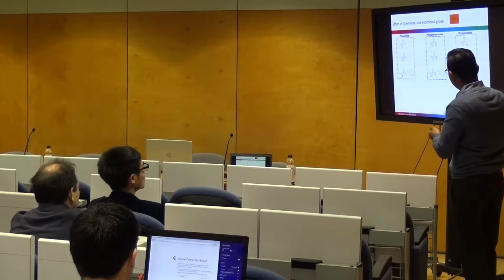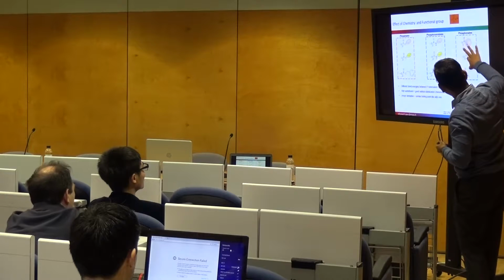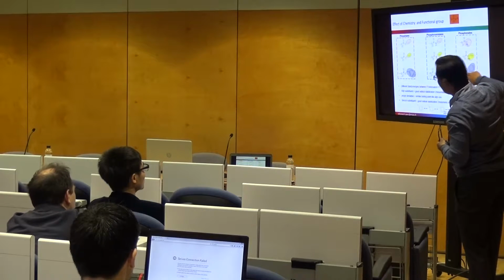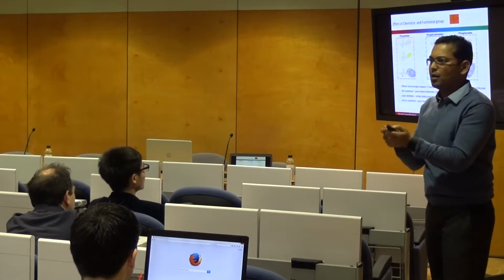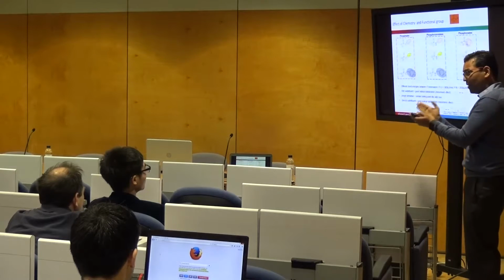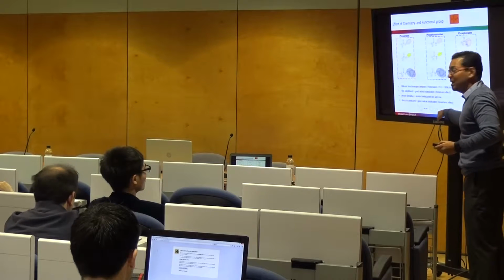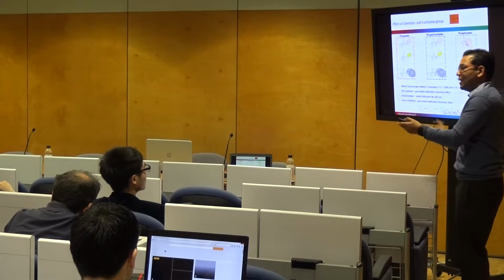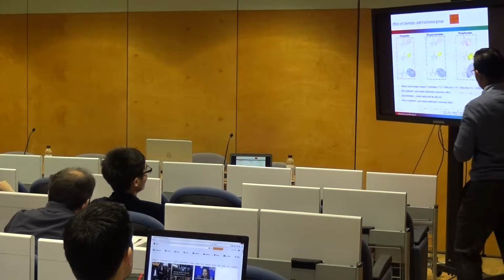Okay? And I don't have to go into details, but there is a reason why we took these special groups, I would say. You can see the allyls and the benzyls are very good leaving groups as radicals. So when you heat up a material, additive, if you have an allyl group or a benzyl group, they cleave off because of the radical stabilizing effect of the allyl and benzylic radicals. Okay? And that was the idea. So if you have something which splits quite easily, goes away, you end up having a phosphoryl radical more efficiently. So that was the goal.